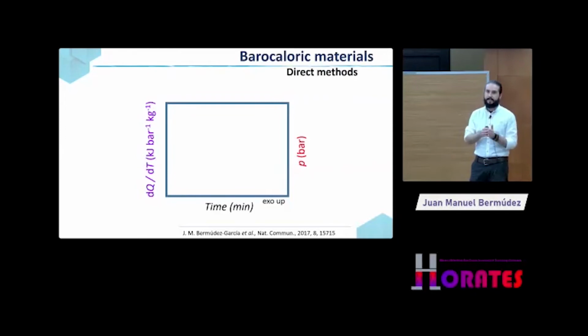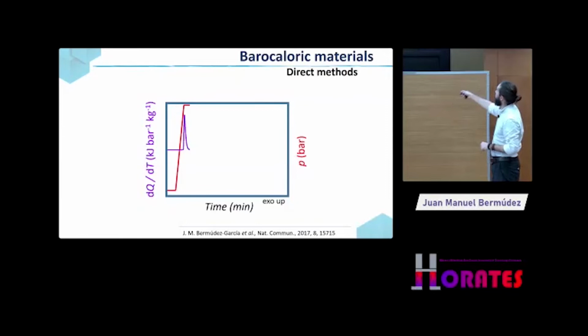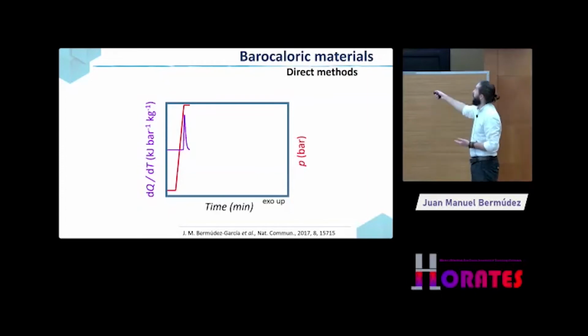They cannot do ramps. So in this way, you can put your material in the high temperature phase, and then you pressurize the material and drive the transition towards the low temperature phase by increasing the pressure. Here you have pressure, here you have the heat flow. And then you reach a pressure where the material drives this phase transition, right? So you can calculate from here directly the enthalpy and entropy change, which is associated to your material under pressurization.